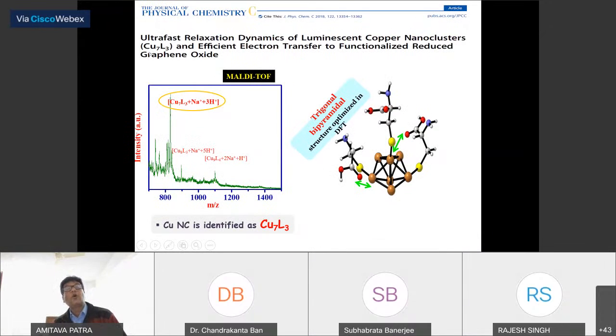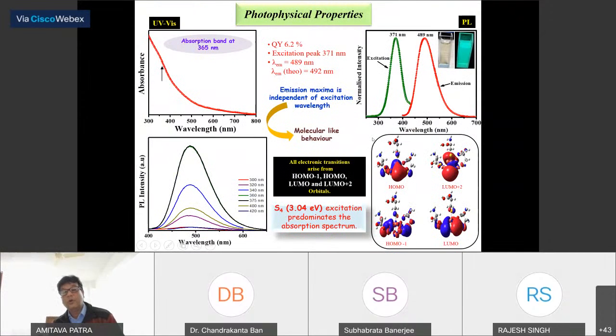So this is one copper cluster, only 7 atoms of cluster and 3 ligands, identified by MALDI. We measured it using MALDI and identified the number of atoms, and from the DFT calculation we measured the HOMO-LUMO gap, which is 3.0 eV, because there is no sharp absorption over here, but sharp emission is there.